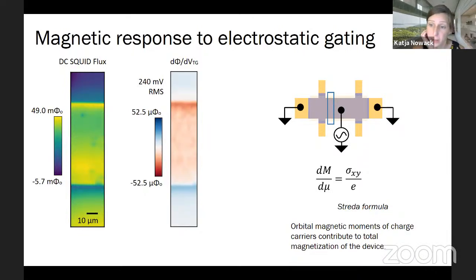We have one other imaging mode on this device, and that is we can modulate the top gate with a small excitation. What that does is modulate slightly the Fermi level or chemical potential in the device. And the reason we might expect a signal is that the Streda formula tells us that we should. The Streda formula tells us that dM/dmu, so how much the magnetization varies with a variation in chemical potential, is given by the transverse conductivity divided by e.